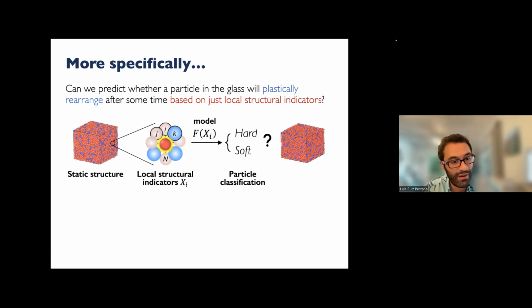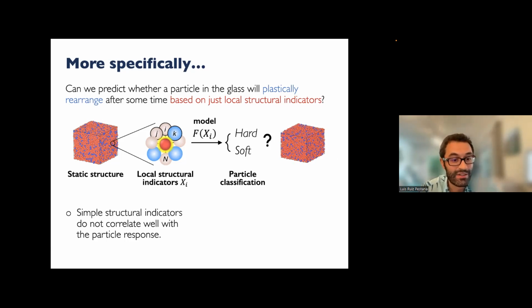So what do we know so far? Well, we know that simple structural indicators do not correlate well with the particle response. I will show you some quantitative information about what this means. A simple structural indicator would be, for example, the number of neighbors within some cutoff distance. If you try to predict whether a particle is hard or soft based on that simple metric, you are not going to be able to do that. Your model is going to be very poor. So people have been trying to find this correlation, what I call here the model f of xi, forever, right? And we haven't been able to make it work.